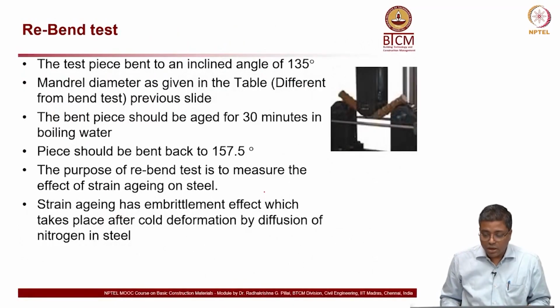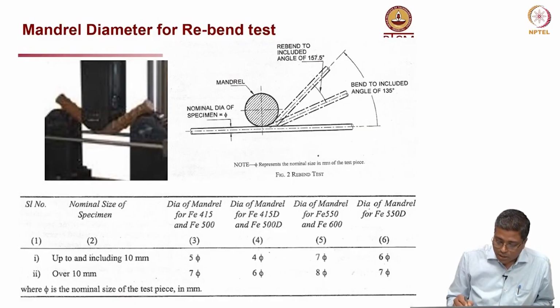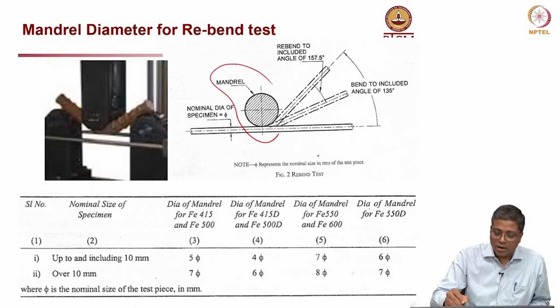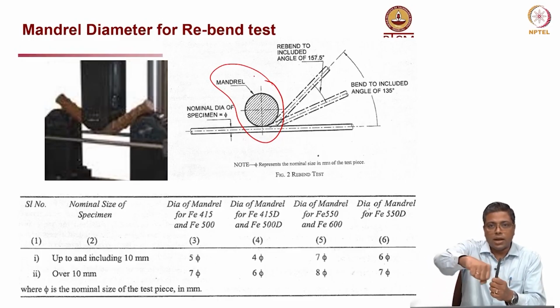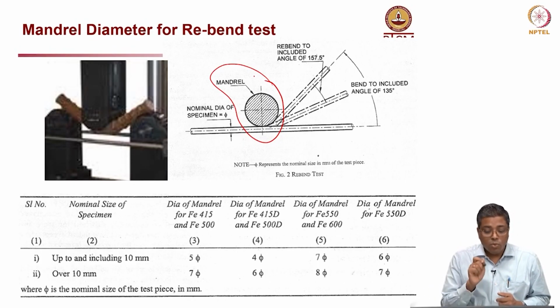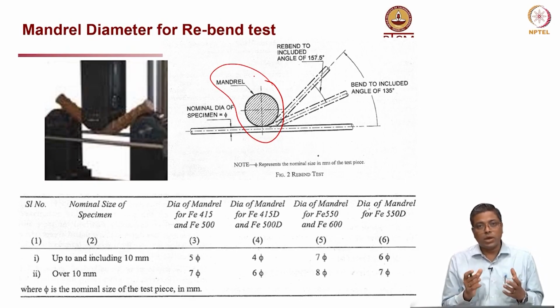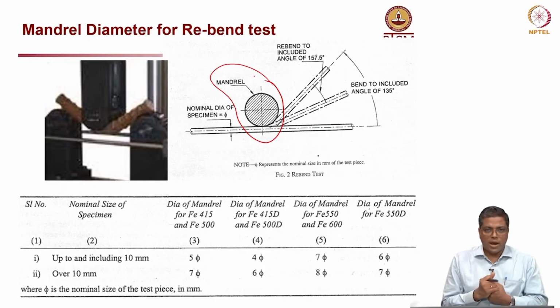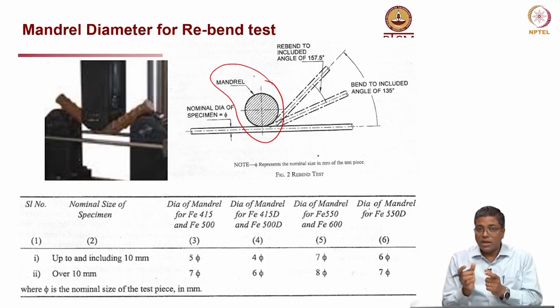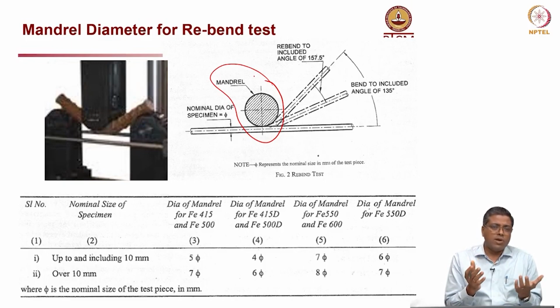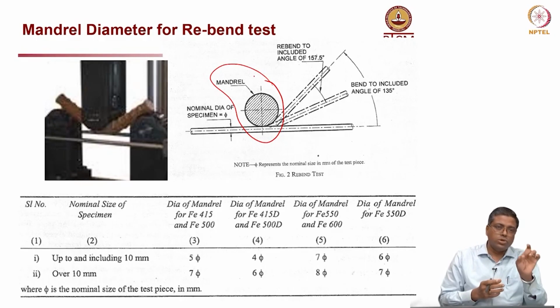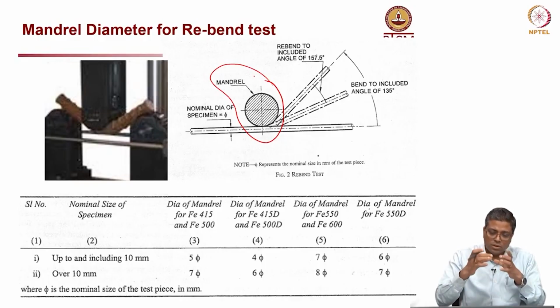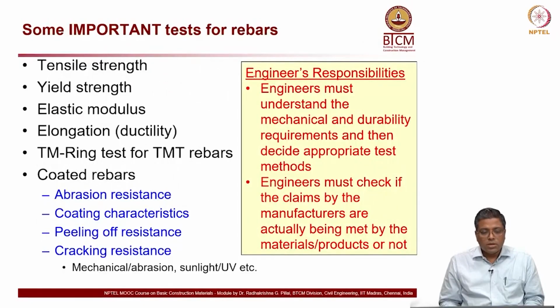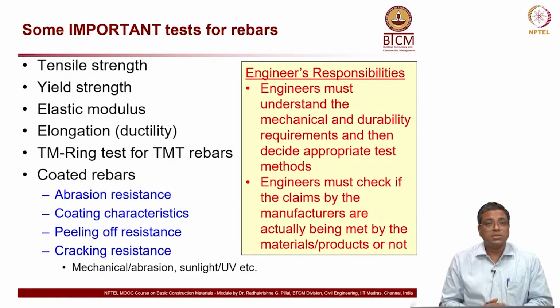This is an example of how the test should be done. But also when you bend it, there is something called a mandrel. So, you put this bar and then try to bend it around that mandrel. Why I am showing this here is, I have seen many places where they bend the bar with a very small mandrel. So, the bending will be very sharp, and when you have a very sharp bend, the bars will crack. So, there are recommended mandrels also, like at the site when you bend the bar, you should use a sufficiently wide diameter for bending purpose. These are very important tests for various rebars.